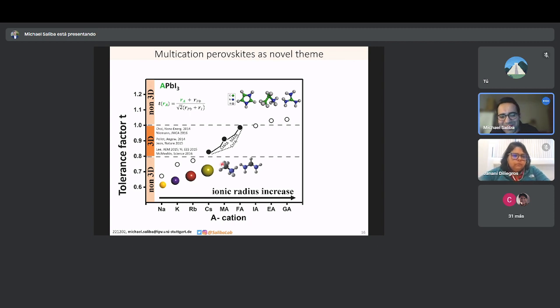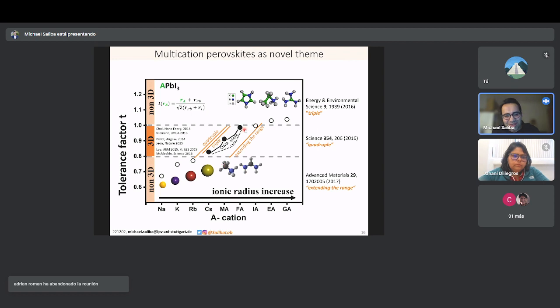And so the idea was to use all three together as a triple cation approach, to treat these three cations, described in literature as space vectors, and to linearly combine them. And the consequence would be the triple cation, which wasn't described in literature then, a quadruple by using a slightly smaller cation compared to cesium, and then slightly larger cations compared to formamidinium, to use this mixing and alloying approach rigorously. So this is the roadmap. And how did that go?